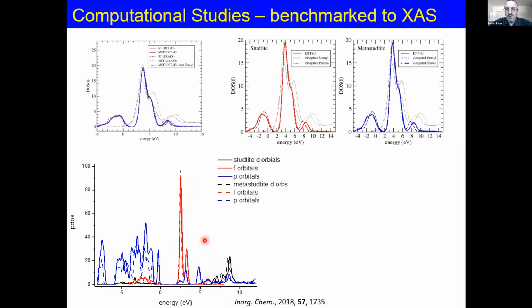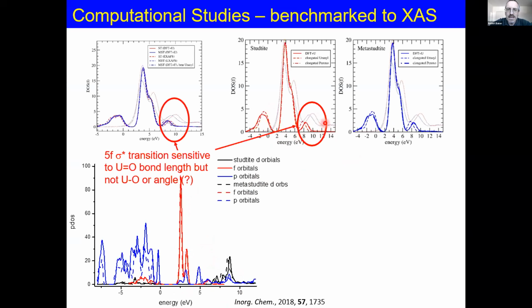What we can do in silico now are things that we can't really do experimentally, and we've bent things and elongated things to see what happens to the spectra. And I draw your attention again to this sigma star transition, because this seems to be the one that's only sensitive to any changes in the structures. And this seems to be sensitive only to the uranyl bond length, not the equatorial bonds, which are expected, but not the angle either, which is quite unusual and a bit of a surprise. So we can't really probe the uranium oxygen in any more detail using the uranium side.